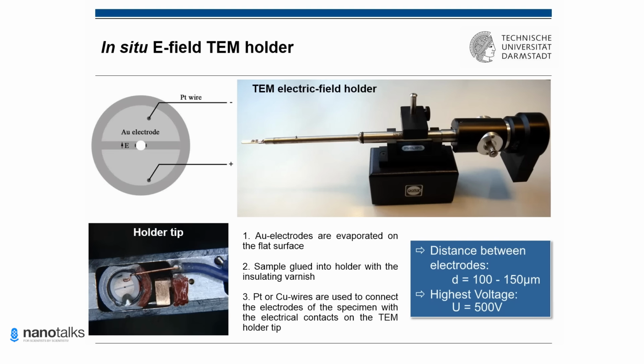So what else? I forgot to mention that the electric field in the TEM specimen is not uniform due to the presence of this central perforation. Basically, the highest field is in these darker areas of the sample, where we perform all our experiments and take images. The actual value of the electric field is not known, and it is calculated from the distance and the voltage, which you can see here.